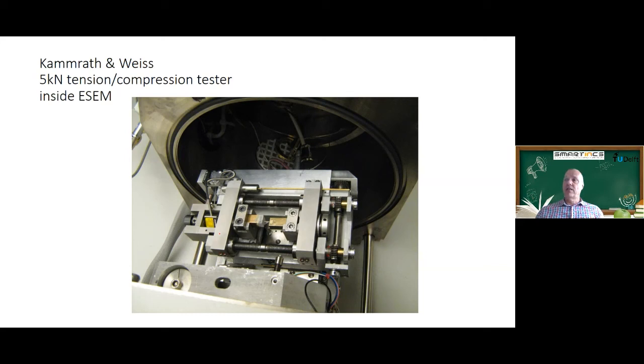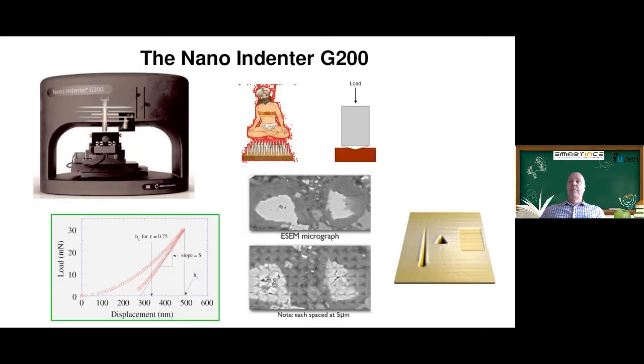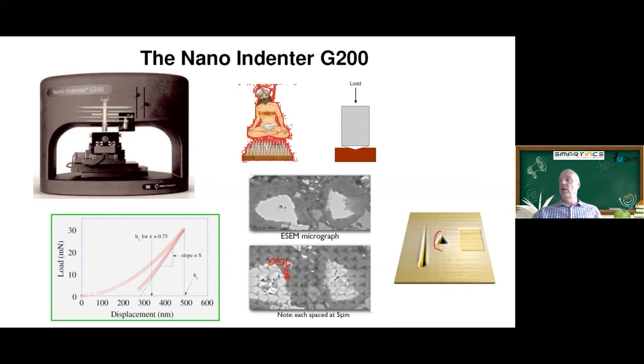Another small-scale test is the pullout of a single fiber from a cement matrix — done inside the electron microscope to see how the fibers pull out and measure the pullout strength. We can go even smaller using the nano-indenter — as shown in yesterday's video — to make indents in a small sample. These are actually two cement grains where you can do small indents and measure the stiffness and hardness locally. You can also make a scratch, and then see how those scratches or indents are filled with your self-healing agent — a way to study self-healing on the micro-scale and visualize it.